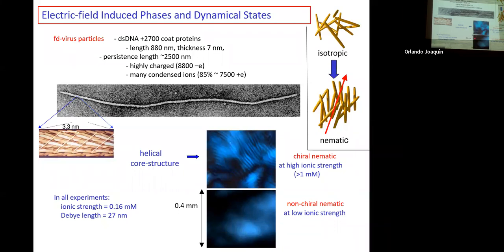normal nematic and the cholesteric nematic where you see the stripes. So the dark area here is most of the time isotropic. So we are going to talk about the system, which is in the two-phase coexistence region, where you have a coexistence between an isotropic phase and a nematic phase. So this is a nematic domain floating in an isotropic environment. So this is within the two-phase region, isotropic-nematic.